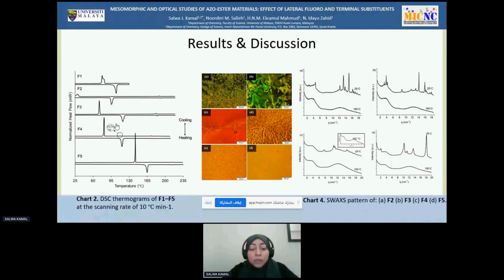transition peaks, from crystal to nematic phase, then from nematic to another nematic phase, then to isotropic phase, both with schlieren texture. Compound F5 with the nitro terminal substituent showed two transition peaks, from crystal to nematic phase, and from nematic to isotropic phase with a higher clearing temperature compared to the other derivatives, with schlieren texture in POM. The first transition for all compounds was confirmed by SWAX experiment.